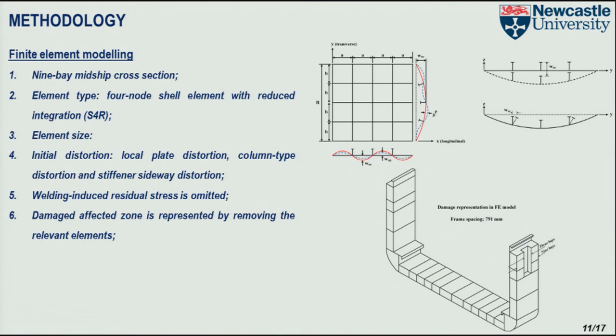As we can see, in the case of sagging, after the peak value, there's still a very large strength remaining on the cross section of our container ship. But in hogging for the intact cross section, there's a relatively large reduction of the strength. But when it comes to damage, the behavior is similar to the behavior in sagging. Those are some comments about the progressive collapse behavior of a container ship in sagging and hogging.